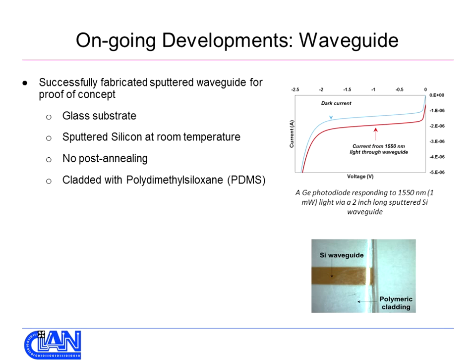Also, we've cladded it with PDMS. Well, ultimately, we wanted to clad with oxide. However, in this controlled test, we actually found, to our surprise, that the waveguide worked. It significantly transmitted 1550 nanometer light. And we tested this with a photodiode, and there on the right, you can see the characteristic on the graph above. Below, you can see the silicon waveguide and the polymer cladding. And that's what we've done so far this year, a couple of weeks ago.